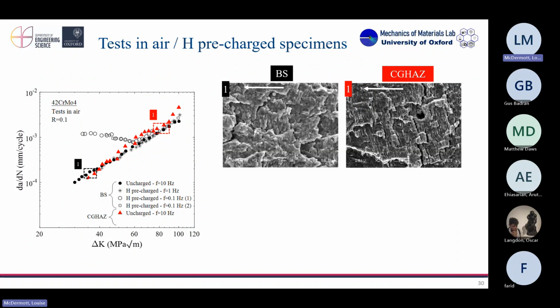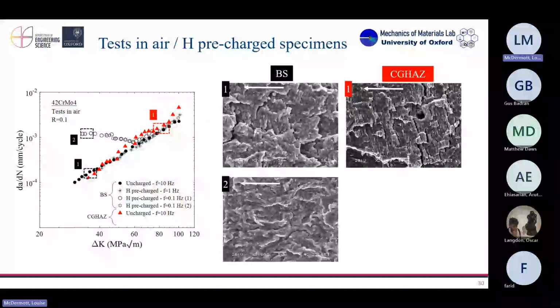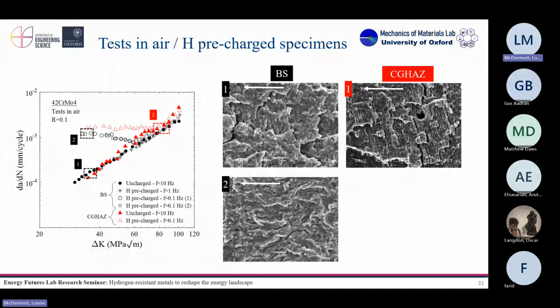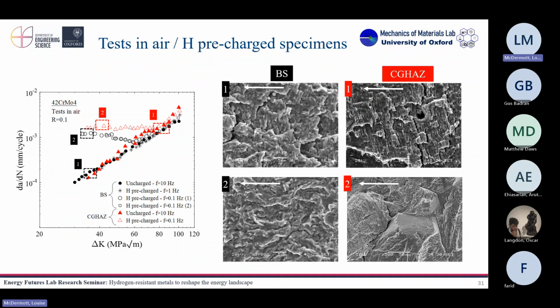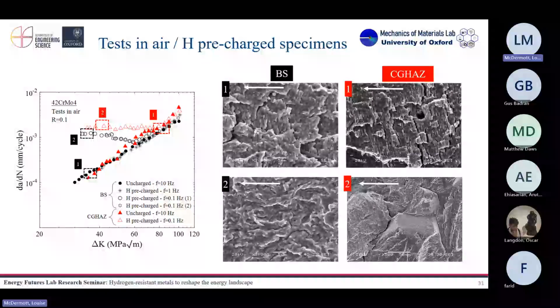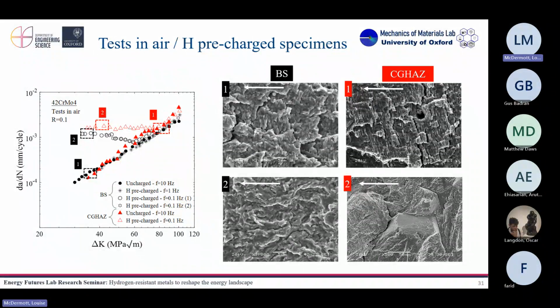Okay, and I did the same with the weld, or with the metal next to the weld, and I observed the same behavior. And it's interesting that when I went to the SEM and checked these two samples, I observed that these striation marks had disappeared. So I couldn't see any sign of, let's say, this ductile crack growth, even though here we still see some ductility in the material far from the weld. But in the material close to the weld, you can even see that we have these intergranular cracks.